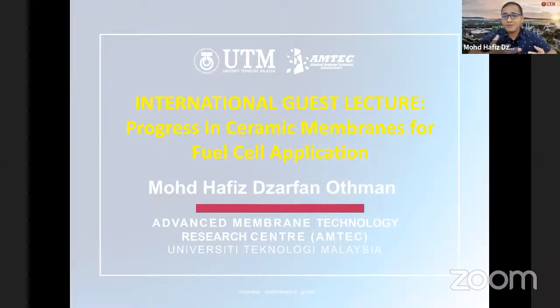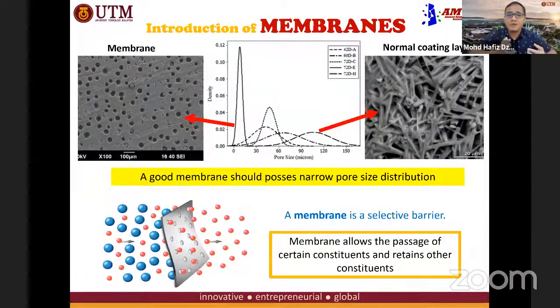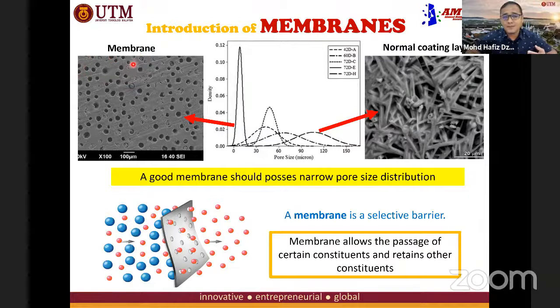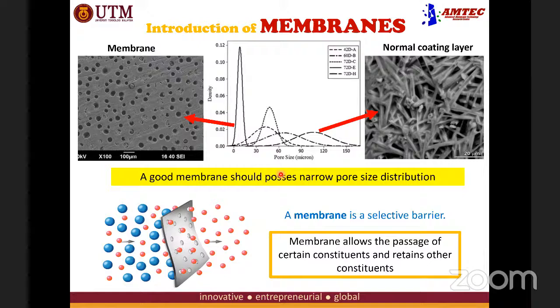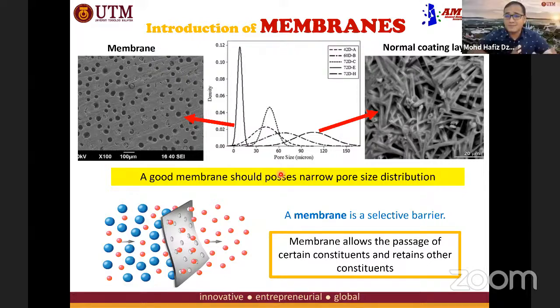So what makes membrane different from a normal coating layer? If you can see from this slide, membrane has a narrow pore size distribution, meaning that its pore size is almost equal throughout the surface. It's not like a normal coating layer, where the pore size distribution is very broad. When it is broad, it doesn't act as a selective barrier. Because membrane has a narrow pore size distribution, it is hard to produce. Therefore, the cost of membrane is normally quite expensive.